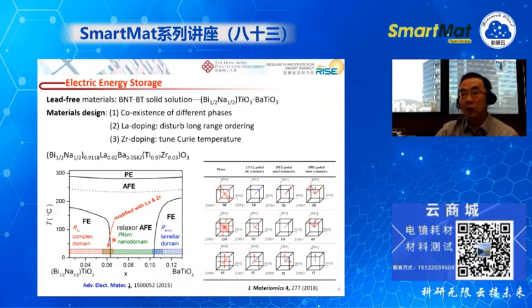And in addition to this coexistence of the two phases, we also add some other elements to modify the composition. We add lanthanum on the A-site of the perovskite. The purpose of this is to disturb the long-range ordering of the polarization state. And we also add a small amount of zirconium on the B-site cations. The purpose of this is to tune the Curie temperature. We want to bring down the Curie temperature. Okay, so finally, the composition we have chosen is this one.